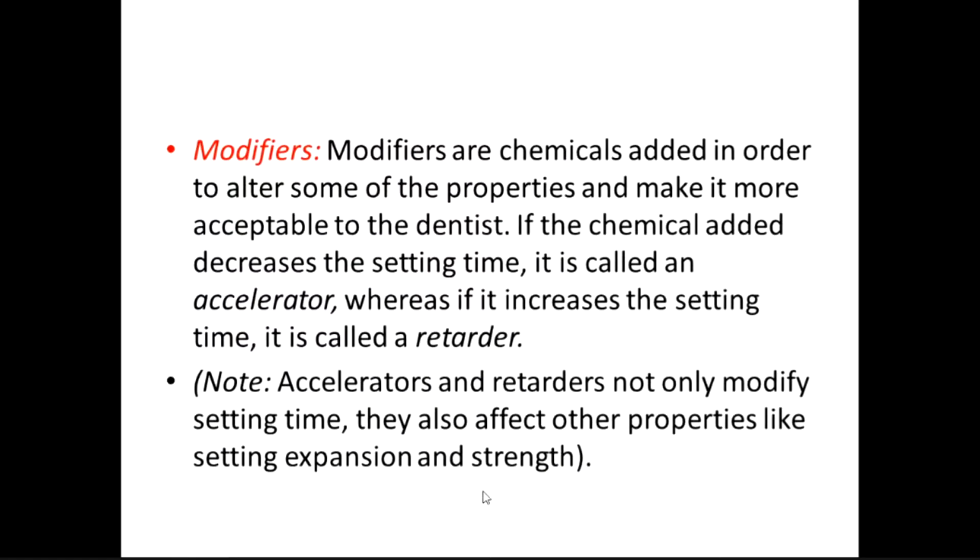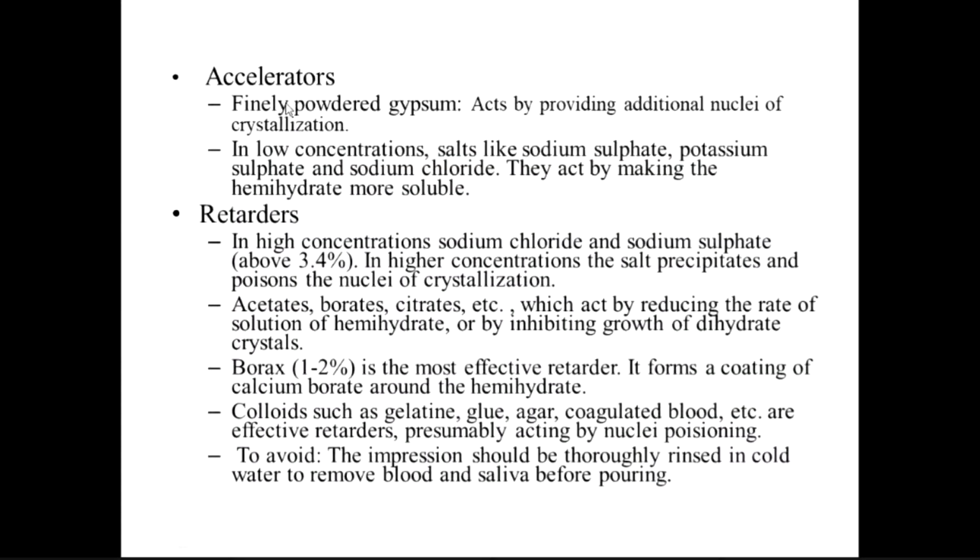You have some modifiers that affect the setting time. You have accelerators. If inserted into the gypsum, they will accelerate the setting time, and vice versa. We have retarders. They will increase the setting time. As we talked, some materials act as accelerators, like salts such as sodium sulfate, potassium sulfate, sodium chloride. They act by making the hemihydrate more soluble, while we have some retarders, like acetate, borate, citrate, borax, colloid, gelatin, glue, agar, coagulated blood.